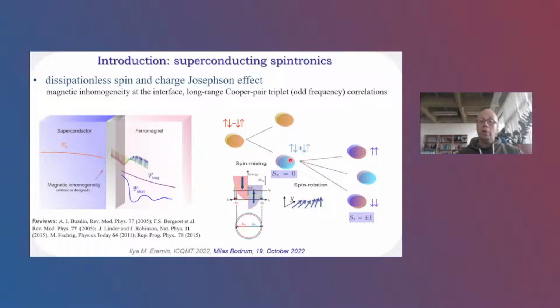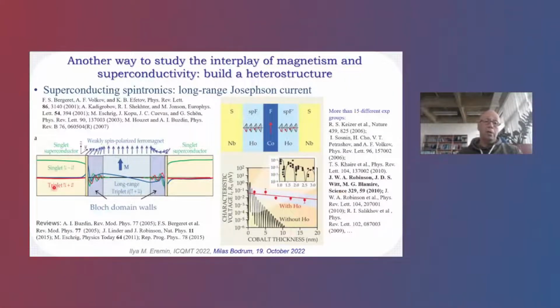What is actually happening is, first you get a spin mixing, and second, because of the rotation of the spin quantization axis, out of the originally spin triplet component with total S equal to 0, you can create a component of the Cooper pair wave function which is spin polarized. And the spin polarized component will be insensitive to the magnetization in your ferromagnet and can penetrate to a large distance. This has been theoretically predicted and also experimentally realized, and a number of groups are working in this field.